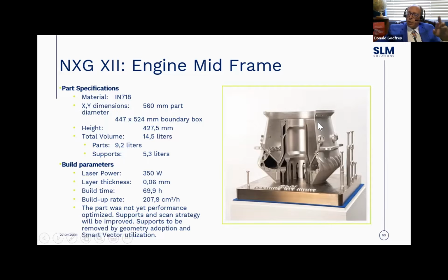So you're going to cut this part up, and we're going to cut tensile specimens out of these parts, because what we want to know is, do the mechanical properties of the part equal the mechanical properties of the test specimen? Now, you don't see it here, but in an approval process, you're going to build these tensile specimens not only around this plate, but you're going to build them inside the part all the way up from top to bottom. And you're going to look at the microstructure of the part, and you're going to look at the microstructure of the specimens, and you're going to tensile test all of them, right?